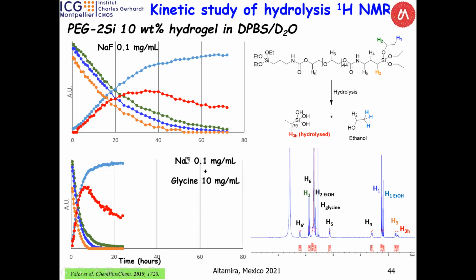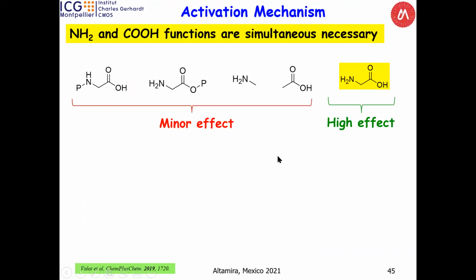However, if you add glycine, 10 milligrams per milliliter, we have exactly the same shape, but it's shifted to shorter time. For instance, here the maximum of hydrolysis is about 40, 45 hours. Here, look, it's between 10 and 12. So you decrease your gelation time very easily, and this can be controlled very well by NMR.